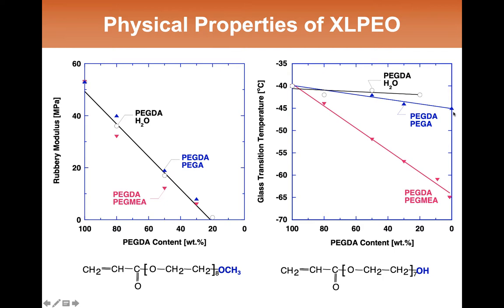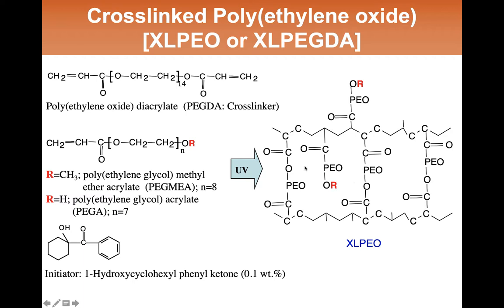On the other hand, if you put this one in, the one with the methyl ether end group on it, and now change the composition, putting more and more of that methyl ether acrylate into the polymerization mixture, you see the glass transition temperature go down and down. And the way this is interpreted is that these side chains are highly flexible. These nonpolar side chains, when they are in this polymer matrix, bring a lot of additional motion.